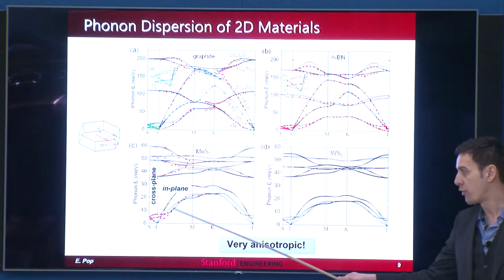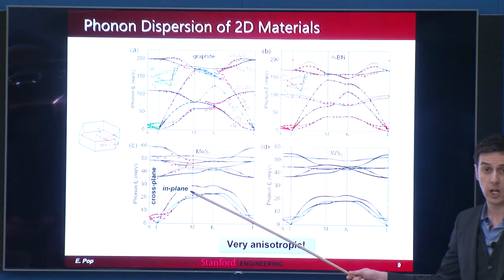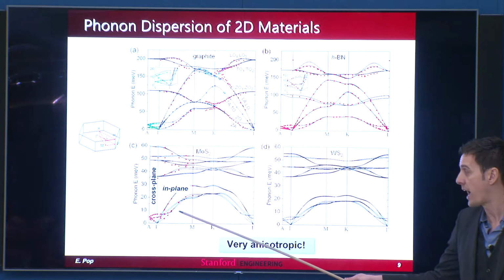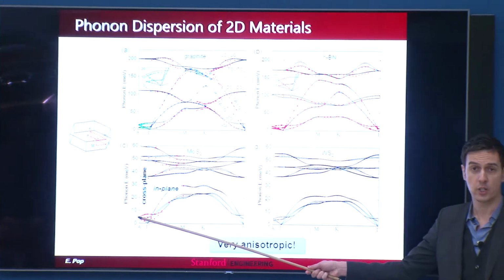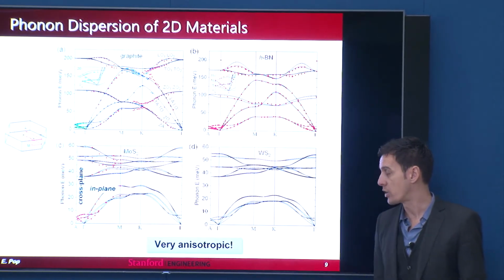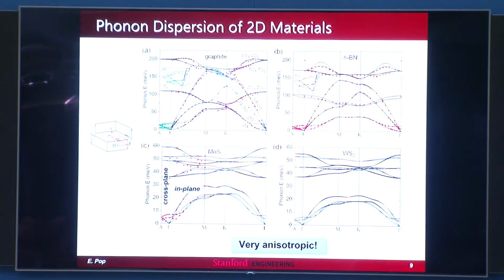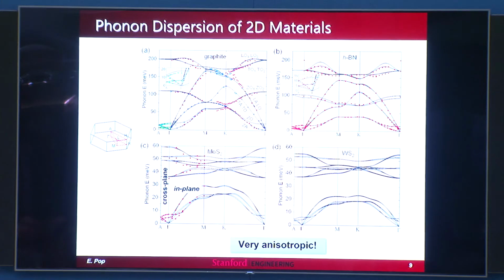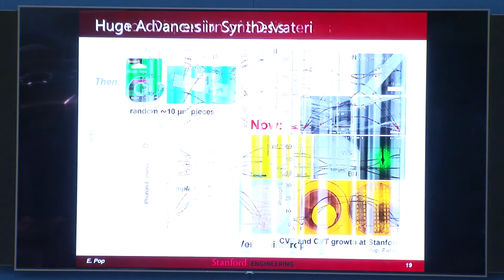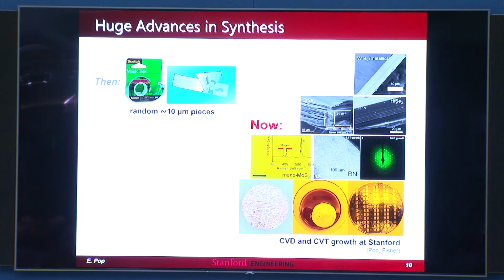If you look in-plane, the phonon velocities are actually pretty good. Heat conduction is quite excellent, in fact. Cross-plane, the heat conduction is actually quite lousy. You can actually see it directly from the phonon group velocities. And so we will be talking about that a little bit later in the talk and how we can leverage that both for good and for evil or bad. Let's hope we don't do anything evil.